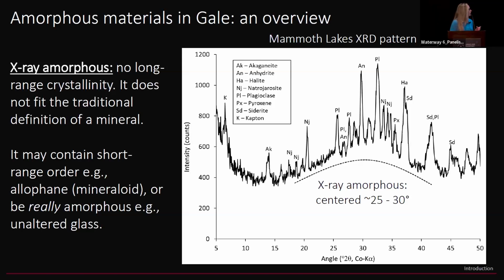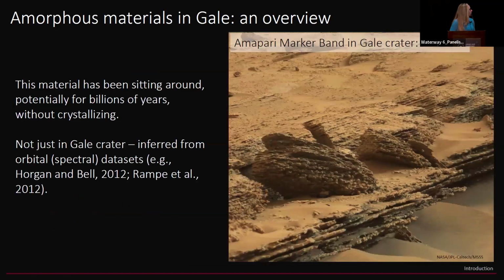So this material could contain short-range order, something along the lines of allophane, which is considered a mineraloid, and less likely, I think, it could be something truly amorphous, like a pristine, totally unaltered glass. But I'm not totally convinced that that is present because it's metastable. So this material has been sitting around potentially for billions of years, and this is an image from the Amapari marker band outcrop in the sulfate unit.